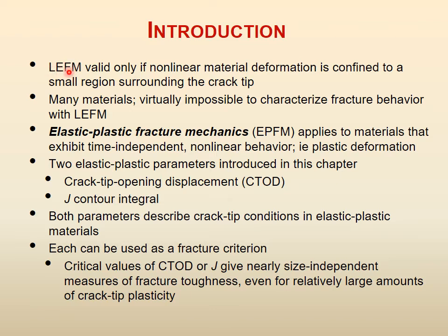LEFM, the linear elastic fracture mechanics, is valid only if the non-linear material deformation is confined to a small region surrounding the crack tip, right? If the non-linear, plastic part is a very small region at the crack tip, then you can still use LEFM. For many materials in the real world, it is virtually impossible to characterize fracture behavior with this LEFM approach.